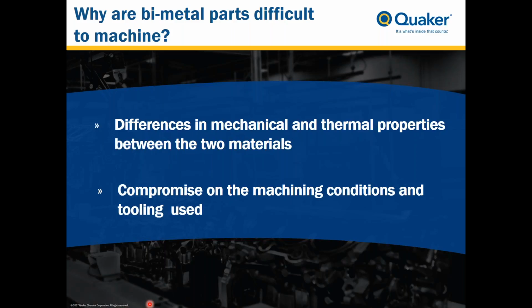The second factor, and it's related to the first in part, is that usually the machining conditions that are necessary to machine a bimetal part are a compromise between those that would be optimum for machining either of them. For example, an aluminum engine block and a cast iron cylinder sleeve. If you were going to machine aluminum by itself, you would probably use significantly different machining conditions, significantly different tooling, maybe tool geometry, maybe even the metalworking fluid, than if you were going to machine cast iron. So again, there's usually a compromise met on the machining conditions, which would then decrease the productivity and the efficiency of the operation.